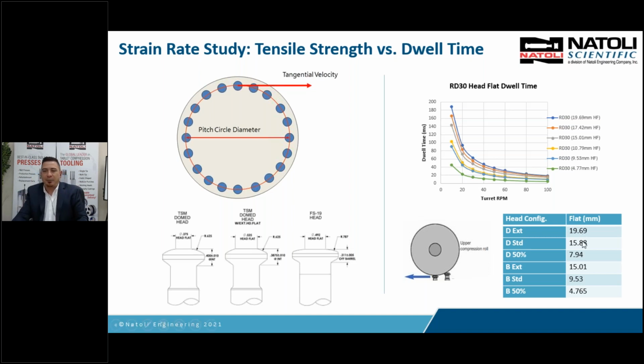In R&D, I would run strain rate studies, and if I found out my material was strain rate sensitive, I know head flat's going to play a major role in the success in manufacturing. So here's examples of different head flats for D and B. And here's an example of these dwell times as a function of turret RPM with these different head flats. So you'll see how the dwell time's influenced by using different head flats.